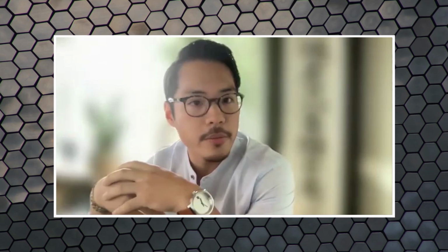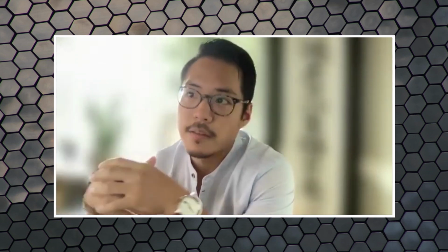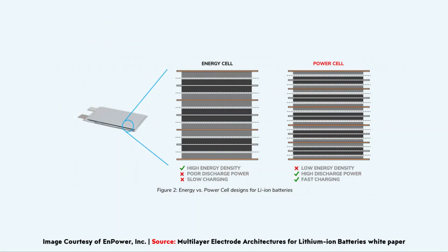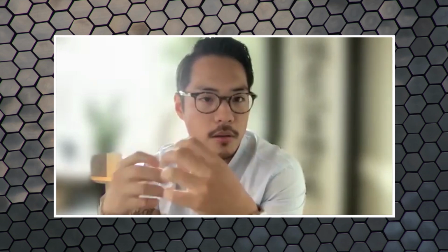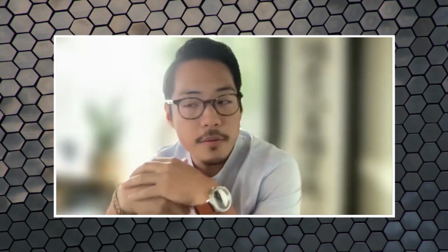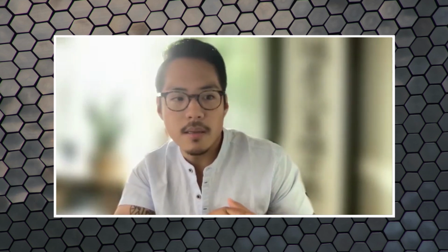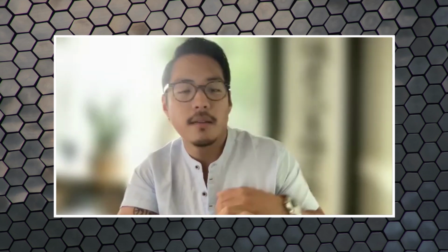Yeah, so like I mentioned earlier, batteries are inherently gradient forming devices, meaning during operation, concentration gradients will form, and that's kind of a fact of life. It's not something that you really want, and so typically to get really high power, you end up making thinner electrodes because the physical distance that lithium ions need to travel will be less, and typically power electrodes are also more porous, so that there's more room in between active material particles like graphite for the lithium ions to move. Of course, when you have thin electrodes, you then have a lot more layers of copper, aluminum, and separator that aren't contributing energy. And because they can also cost more, the power cells are not only less energy dense, they're also generally more costly.